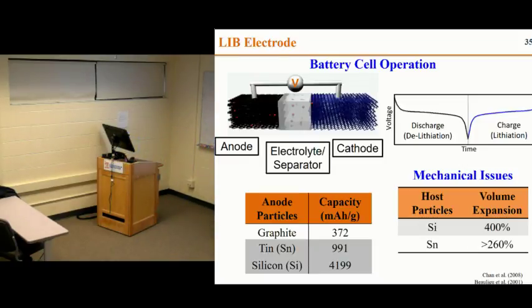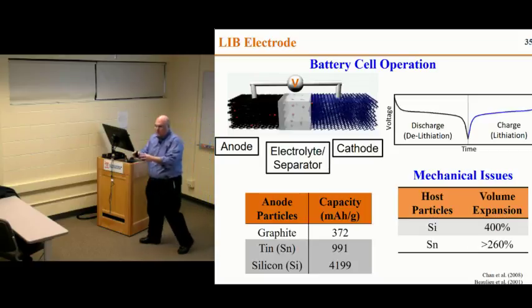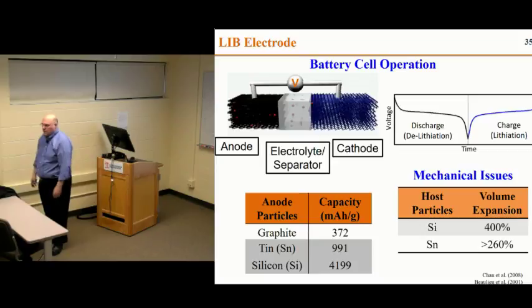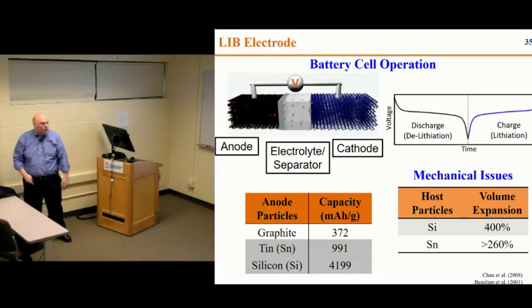Silicon expands by about 400%, and the poor thing just can't take it. So it would just go boom and explode. After a couple of cycles, the battery's dead just because the host particles have completely disintegrated.